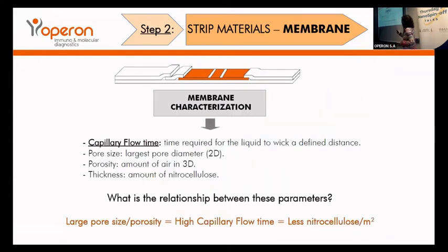It's important to know the main parameters that characterize the membrane. The first one is the capillary flow time. Most manufacturers make this parameter available so you can compare between different membranes. It is defined as the time required for a liquid, usually water, to wick a defined distance, usually 4 centimeters. Other parameters are the pore size, the porosity, and the thickness. What is the relationship between these parameters? In an ideal situation, a large pore size and porosity mean a low capillary flow time and less nitrocellulose per square meter.